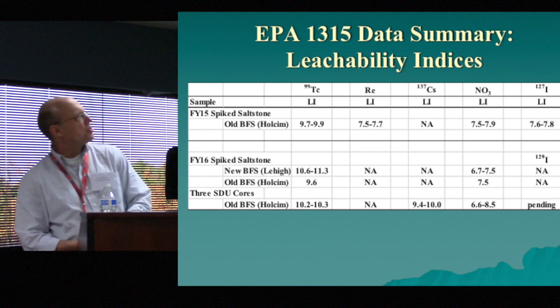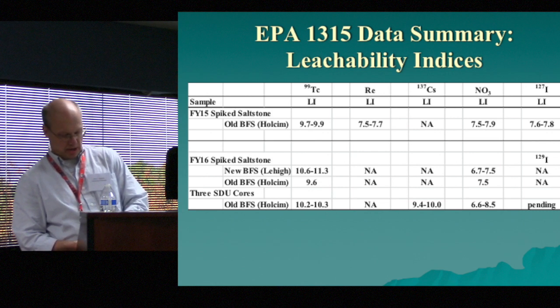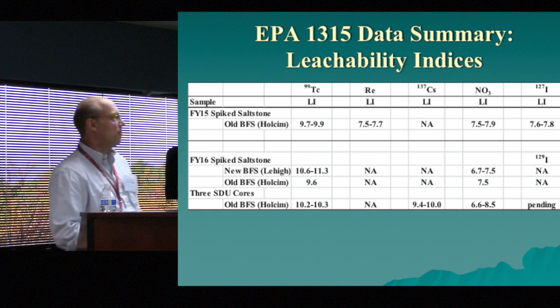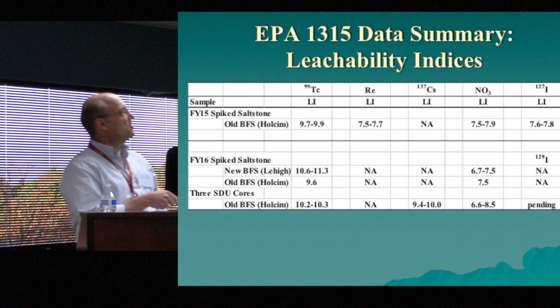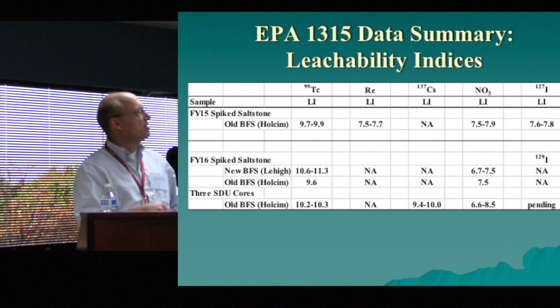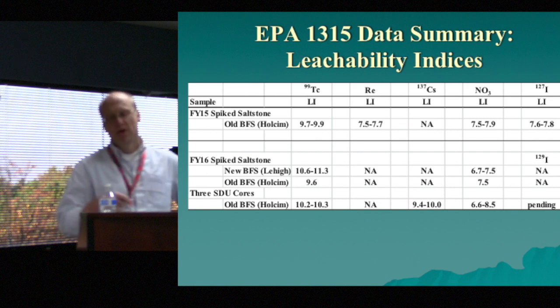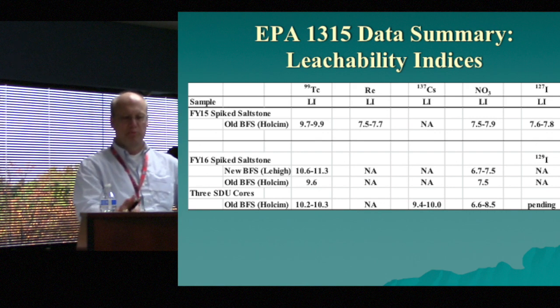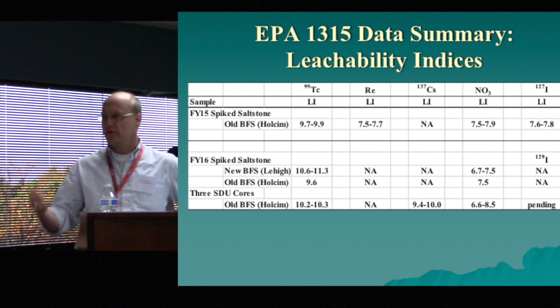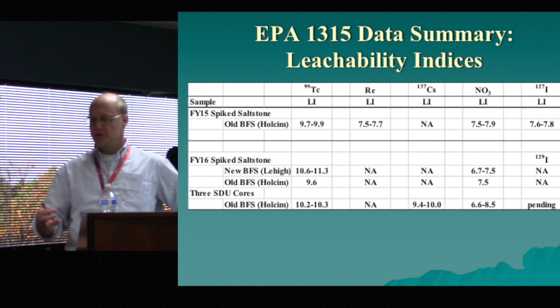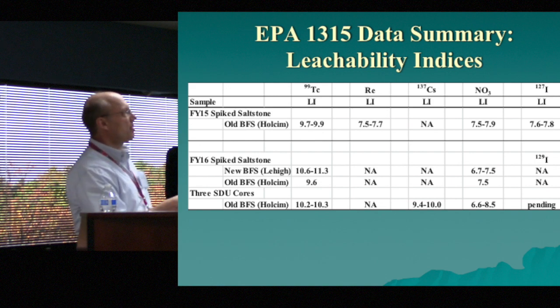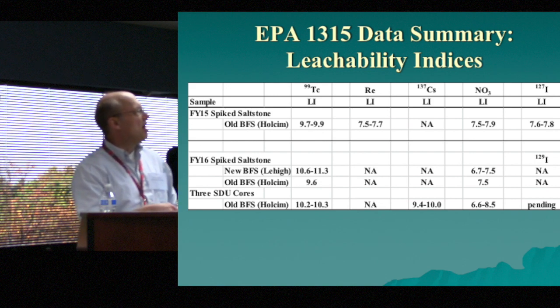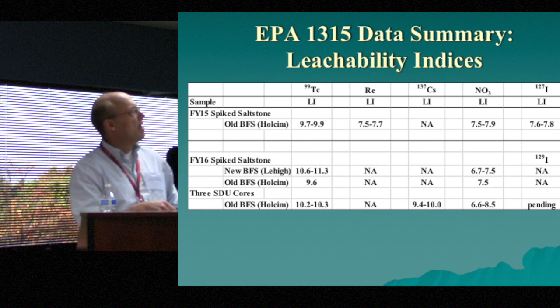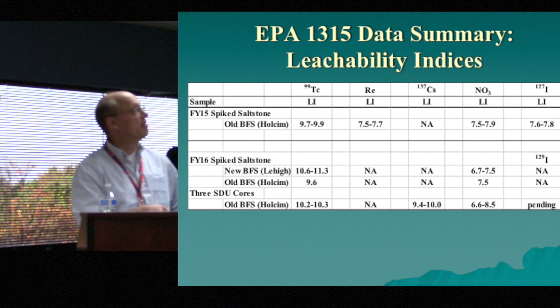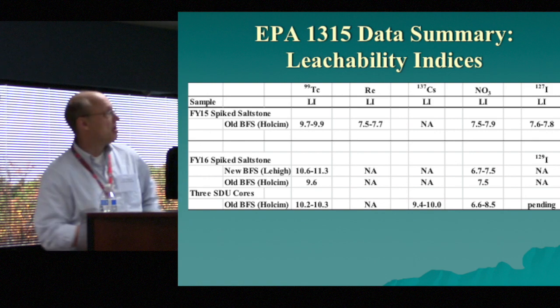So this is just to summarize the leachability indices for all of these studies. And what we found is the ranges up here represent more than 6 different measurements. I'm not going to call them reps because all of these include all of the different atmospheres. It's all bulked together. And what we find is close to 10 for technetium, around 7, 7.5 for rhenium, nitrate about 7, 7.5, and iodine about 7.5 as well.